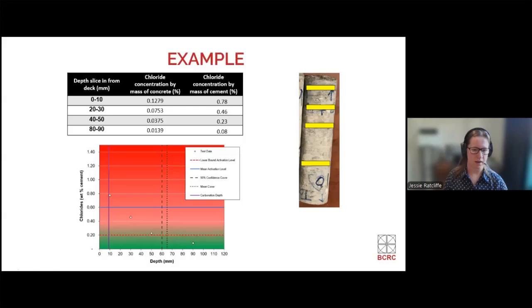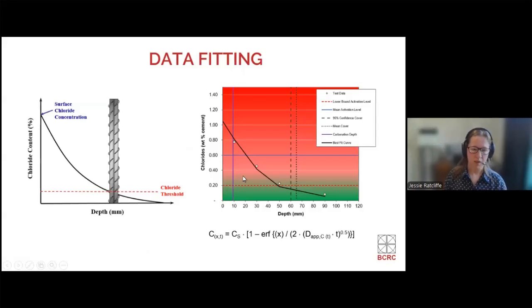So say this is our core and we've sliced it at the level shown on the left. We have this chloride data as weight of cement. We can plot it. You can already see a curve sort of appearing. And then using our equation from the model code and the least squares method, we can fit that curve and find our apparent diffusion coefficient.